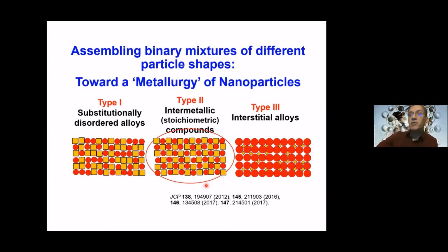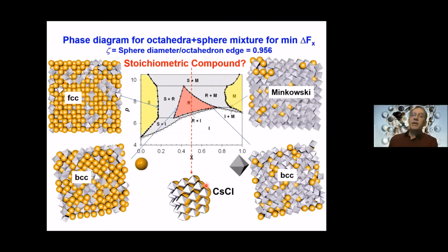Now, this may be a good point to ask the question, how about an intermetallic compound? So in this system, I could have expected to see at the equimolar composition this cesium chloride structure that corresponds to a compound that will look something like this. And at least for this size ratio and for the pressures we could simulate, we never saw this structure.